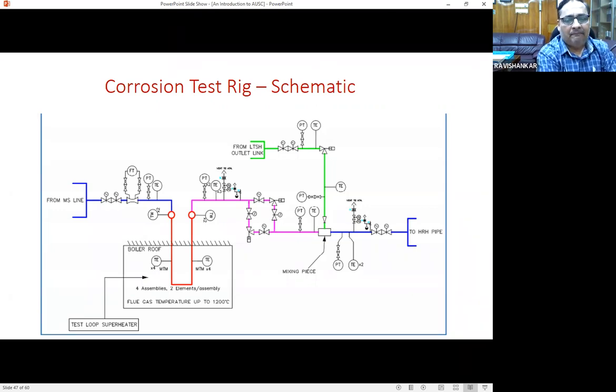So that lower temperature steam of 540 degree plus or minus 15 degree, pressure 45, is joined to the hot reheat pipe and is recirculated in the boiler. The flow taken was around 20 tons, sir. And you can see that there are 4 number of assemblies, and each assembly has 2 elements. And the flue gas temperature at this zone is around 1200 degrees centigrade, sir.